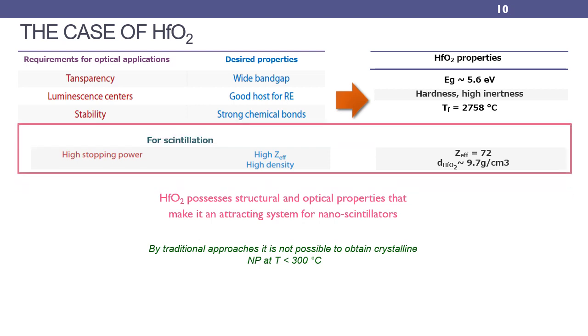The reason of presenting hafnium oxide as a case of study today is due to the appropriateness of its properties also for the optical field and for scintillation. Indeed, being a wide bandgap material, hafnium oxide can be an excellent host for dopants. The high Z number and the high density make hafnium oxide suitable in scintillation because of its ability of stopping the ionizing radiation. For example, hafnium oxide has been recently proposed in oncology as material useful to increase the effect of the traditional radiotherapy.